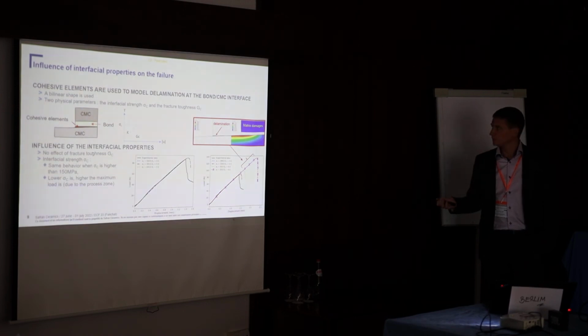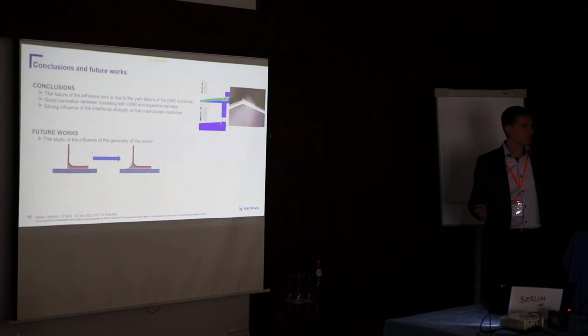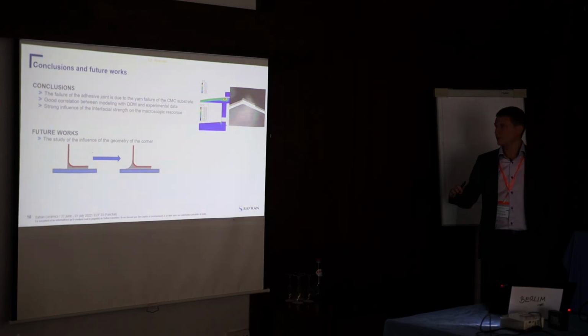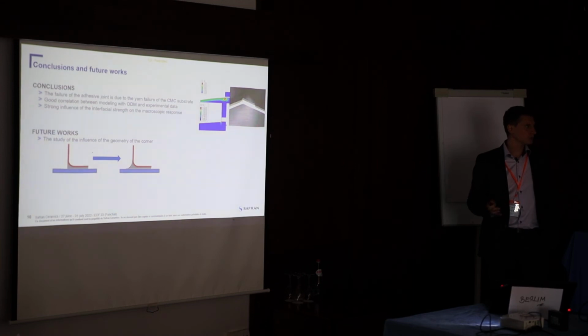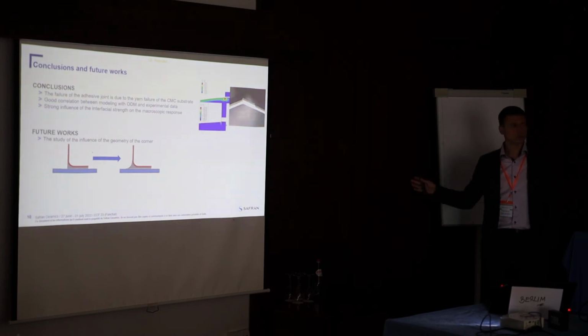Okay, so now we understand where we can have delamination and when we can have yarn failure. So we have not predicted, but we describe the different damage mechanisms with this kind of test. So we can be satisfied because we have a good correlation between the Onera damage model modeling and experimental data, and we have understood the strong influence of the interfacial strength on the macroscopic response.